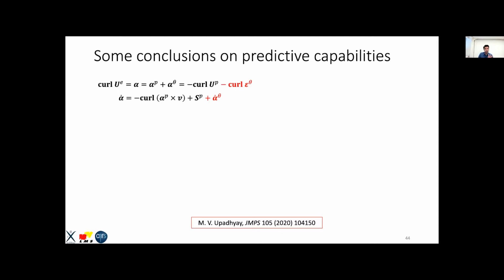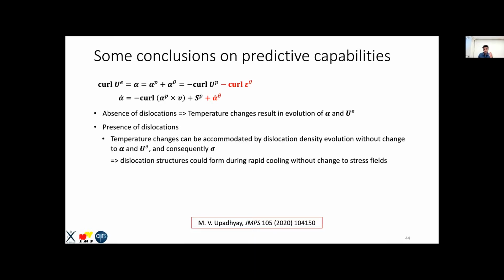To conclude on the predictive capabilities, with these equations you can show that in the absence of dislocations, any temperature changes will result in the evolution of alpha and elastic distortion. That means without the presence of dislocations, temperature changes can be accommodated by stresses that are generated in the material. In the presence of dislocations, temperature changes can be accommodated by dislocation density evolution without changing the stress field.